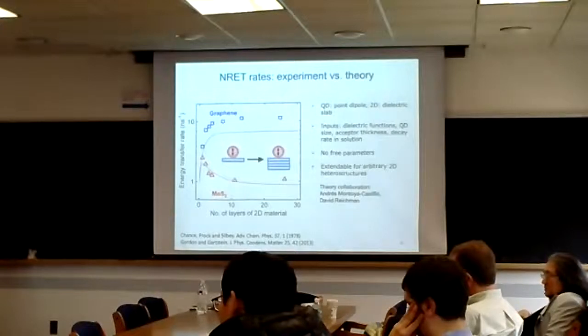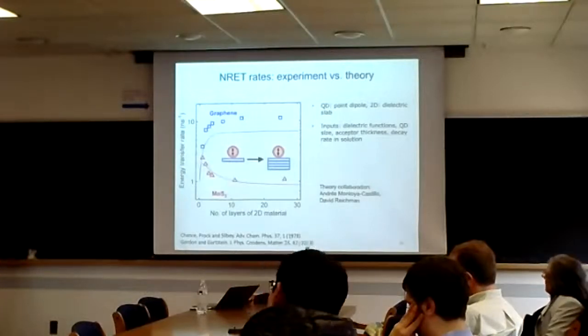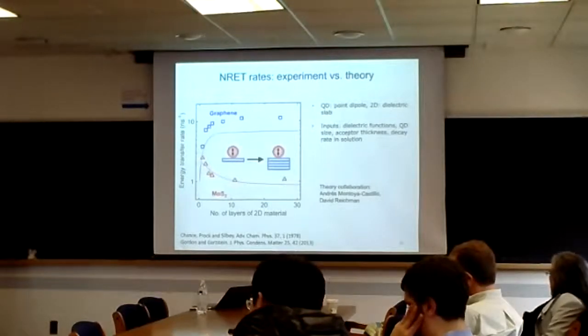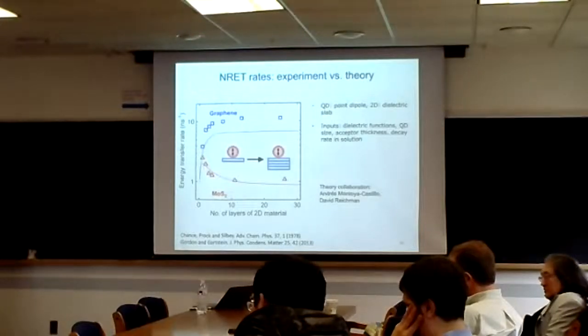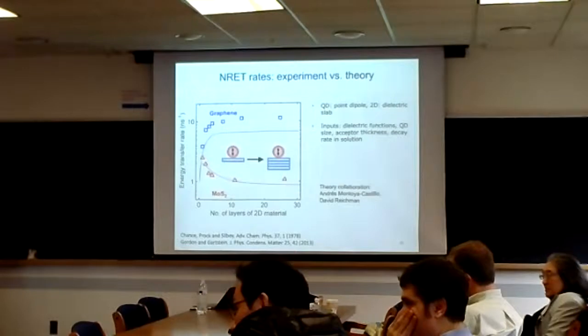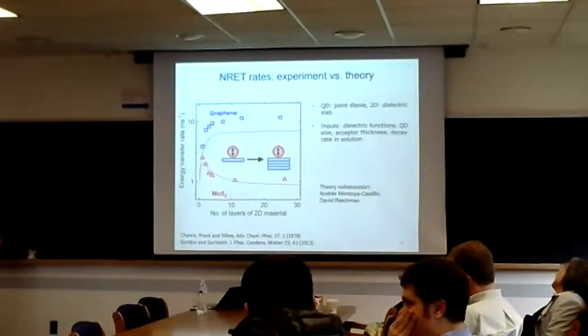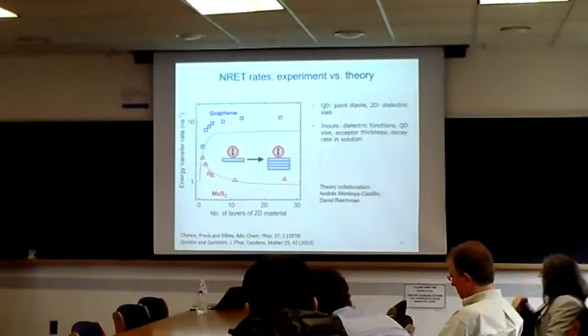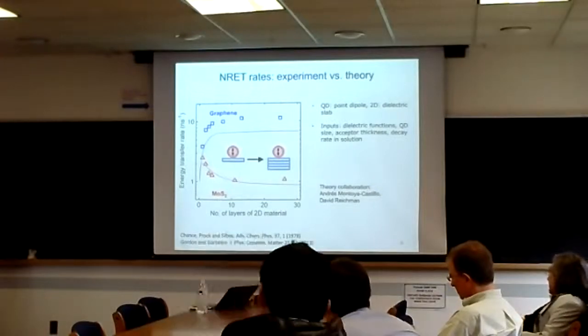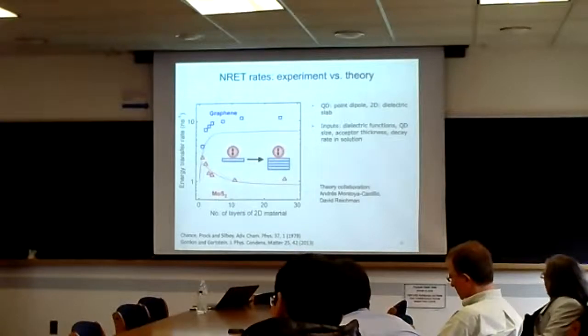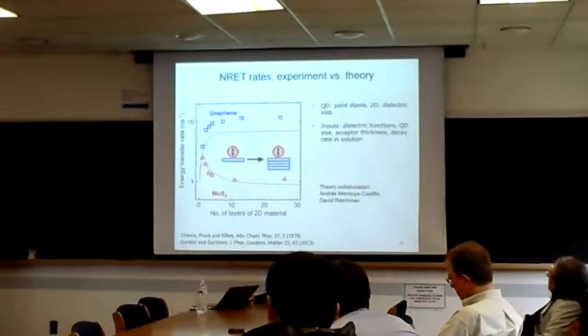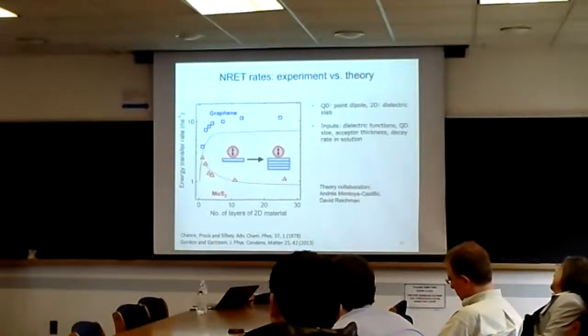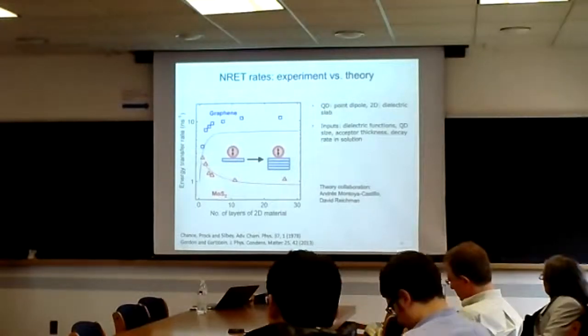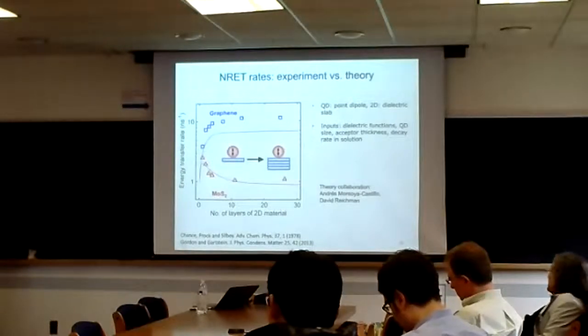And the dielectric functions which you're using, is it what you are modeling or what you are measuring? It's the experimental dielectric function at the energy where the quantum dot sits. So this is measured from some other experiment? Yes, this is existing data for the bulk material. How do you know the out-of-plane data for these few layers? We don't have to; it's the same for the few layers as the bulk. For the in-plane and out-of-plane, there are huge measurements down to fairly low energies. Experimentally, this has been known for many decades for the bulk, and that's the number we're using. The change in the properties of the electronic structure as you make it thin is not important here. What is important is that you can make it very thin and still use the dielectric functions from the bulk.